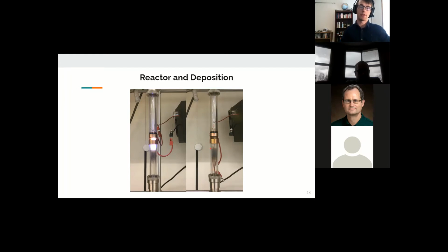Where the powder can be seen collecting lightly on the walls of the reactor, as in this image. The nanocrystal powder collects on the walls downstream of the plasma because there's no opposing force to stop it from doing so. The particles bump into the wall, and no plasma sheath exists to repel the charged nanoparticles. So in this image, you can see the length of the plasma, and where that plasma ends is where the nanoparticle deposition begins.